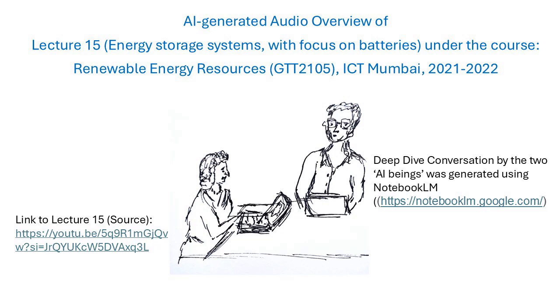Then he highlights a really crucial step towards modern batteries, Matsushita's non-aqueous lithium primary battery. Okay, so Matsushita tackled that voltage limit by ditching water. They used lithium metal as the anode. Super reactive. And a cathode made of fluorinated graphite, CFx. So lithium becomes lithium ions, travels over. At the cathode, electrons react with CFx, fluorine pops out to form lithium fluoride, LiF, and you're left with carbon.